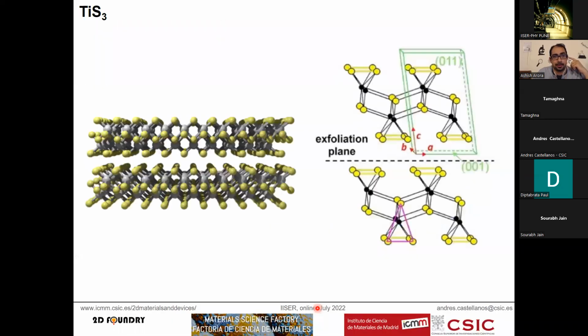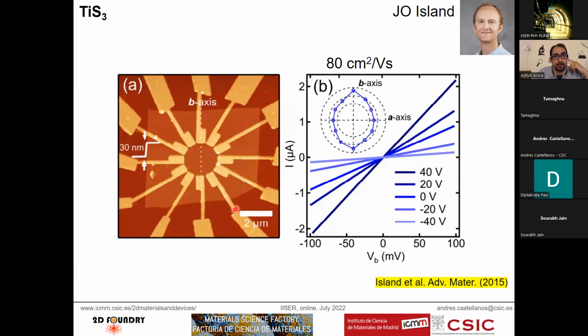Yes. So depending on the temperature you grow it, you can get different aspect ratios. This has been grown at low temperature, so it's basically similar in the two directions. This we call flakes, and the other ones we call ribbons, but they are usually several microns wide and very long. So if you grow at high temperature and you make these ribbons, they can be like 100 microns long and maybe 4 or 5 microns wide.